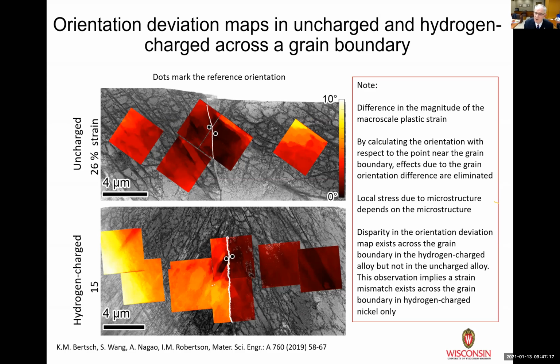Now I ask you to turn to the bottom image and look at the difference there. I do have a different microstructure, but one of the key things I want to point out to you here is look at the stress or the strain evolution on the left side of the grain boundary compared to the right side. And look in particular at the difference right next to that white line that we have, the grain boundary itself. You'll notice that it's dark red on one side, and it's a different shade of red, maybe even orange on the other. What does that tell you? Well, if we look at the scale bar, what it tells you is there's more strain on the left side than there is on the right.